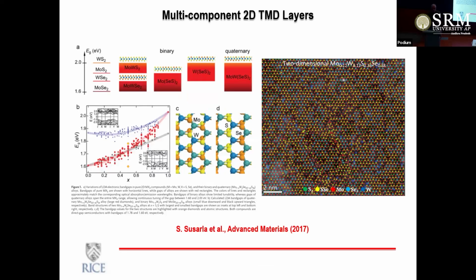And then you can also have multi-compositions, multiple components in these systems. You can have alloys, for example. So this is a very interesting material that we made in our lab that has 4 components: molybdenum, tungsten, sulfur, selenium. And they are very similar as they mix pretty well. And you can see on the right-hand side, this atomically thin layer that is imaged with atomic resolution.